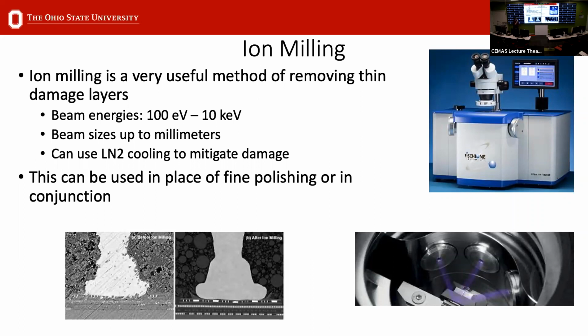So with higher energies, what you typically want to do, just like you would in polishing, is do a rougher ion milling with a higher energy, and then progressively work your way down. One thing that I didn't put here that you can also do is change the angle of your guns to be at a steeper angle or a shallower angle, and as you get to the shallower angle, that helps get the top layers polished. And you can see one example here of before and after ion milling, which makes a significant difference in your sample quality, with the added advantage that you don't have to worry about things like polishing, where you might introduce deformation into your materials. So this is definitely an option for some sample preparation.